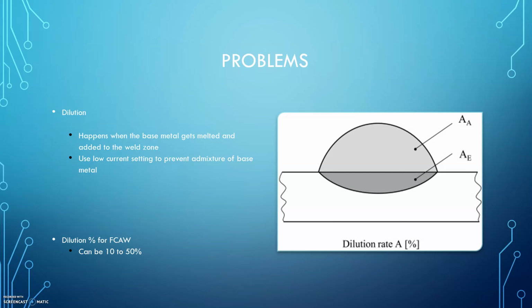Dilution can be an issue with flux cord hard facing. This happens when the base metal gets too hot and mixes too much with the weld metal and leads to micro cracks near the welding line. 100% CO2 increases penetration, which can increase problems with dilution. Best way to control dilution is to try to use low current settings.